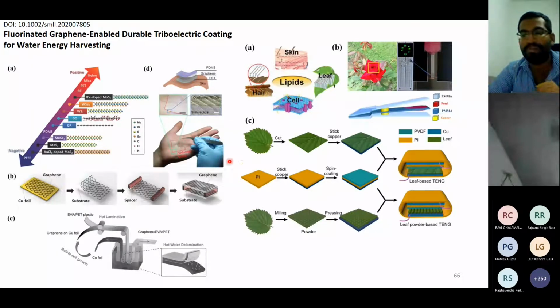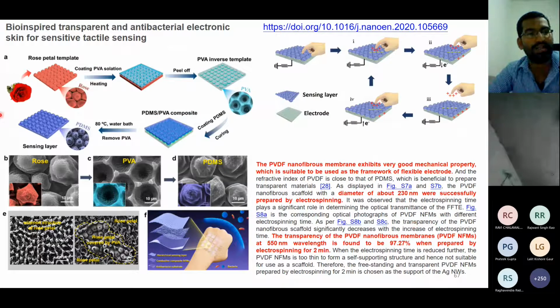You can see how they fabricate this kind of TENG structure using some natural-based materials. So we can also try this kind of structure. It is possible to do. We should know that the distance and the dielectric properties of the two dielectric materials are quite important, as is the maintenance of surface charge density using microstructures. For example, here you can see they adapted rose petal structures. They use rose petal templates to form this kind of structure, and then use it for triboelectricity generation.